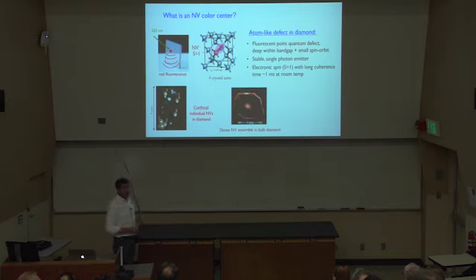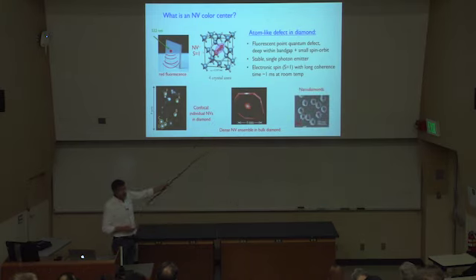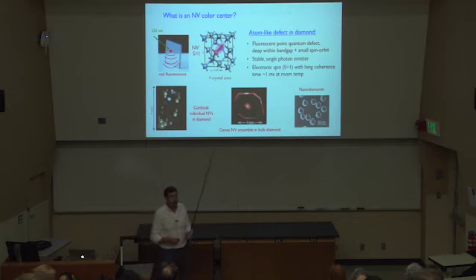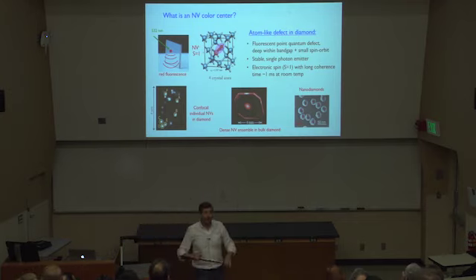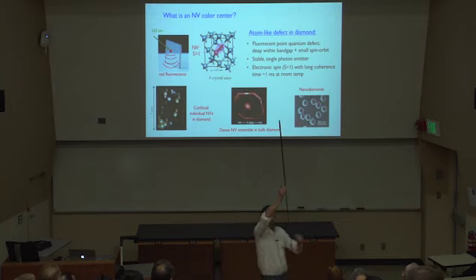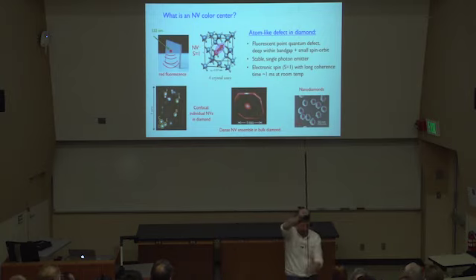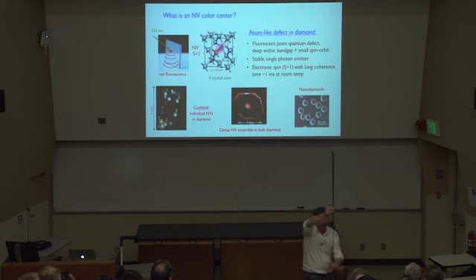individually. Or you can have very high density of NVs so that the diamond is visibly purpley almost to black, and when you hit with green it glows red. You can choose the NVs to be located inside of small nanodiamonds, which can be very small. You can fabricate nanodiamonds of various shapes. Sometimes you make them in a pillar, and you have a single NV, like this ball at the bottom here. You attach it to an atomic force microscope and scan around a sample of interest to make measurements, right?